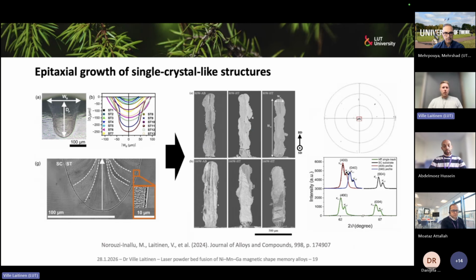Then the other approach we can take is to try to get more of this coarse grain structure. We could use epitaxial growth. This is of course limiting the geometry you can make, because this epitaxial growth cannot be achieved in any possible geometry. We have some limitations related to it.